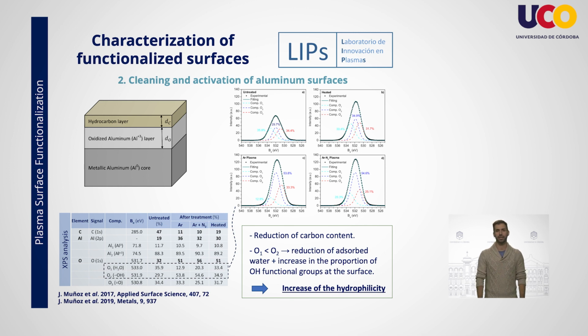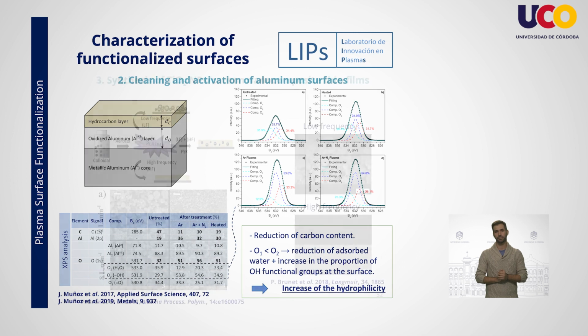From the spectra, it can be observed that, as compared to the heating processing, the post-discharge treatment removes the water absorbed in the surface, whereas it increases the contribution of hydroxide groups. Therefore, we can conclude that both the removal of the hydrocarbon layer and the incorporation of hydroxide groups in the surface are responsible for the cleaning of the surface, and this is only due to the plasma treatment.